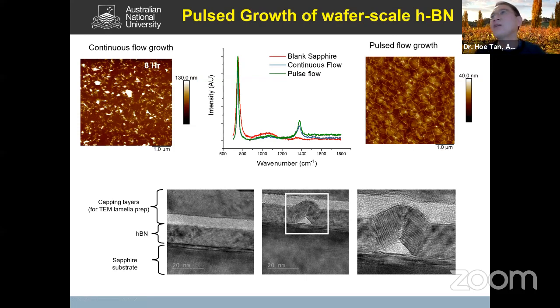And these wrinkles, they are not actually cracked, they are wrinkled. As you can see here, this is the TEM image. So you can see here, this is a sapphire substrate. And you can see this layer by layer growth of the hexagonal boron nitride, which is a 2D material. And we are lucky to be able to see one of the regions here at the wrinkle region. You can see here, the film does not crack. Okay, so they just wrinkle. Okay, it's still a continuous film, but it's just wrinkled.